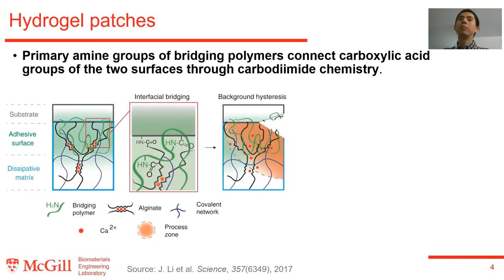Hydrogels are soft and biocompatible and are widely used as wound healing dressings. However, adhering hydrogel to tissue is difficult. To overcome this challenge, our lab previously developed a strategy relying on two key points. One is to use a biocompatible adhesive reagent to form covalent bonds between the hydrogel and the tissue. And the other one is to increase the energy dissipation inside the hydrogel.